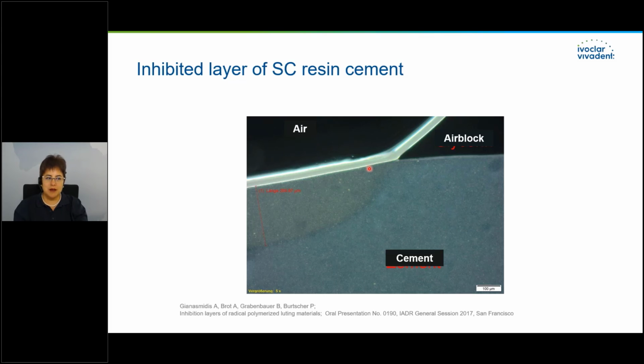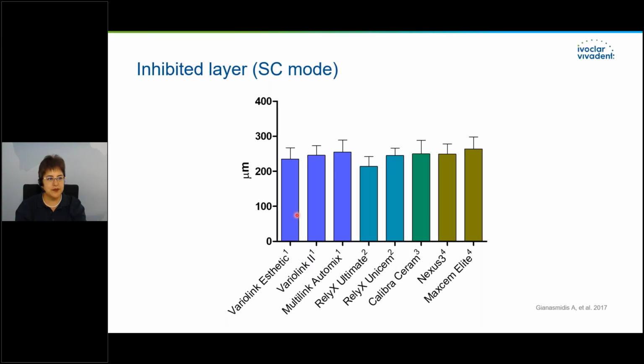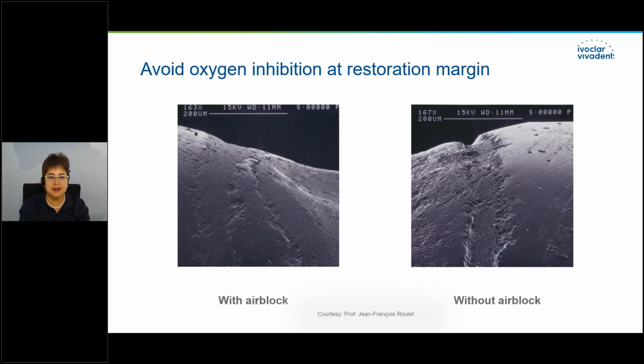If you are not applying it, then you will have a gap of around 265 microns of uncured resin on your margins. And this uncured material can lead to stainings and decolorations on your margins, and nobody wants this. Here also, using self-curing mode, you see the oxygen inhibition layer is around 200 microns or more depending on the material. If you light cure the material, this thickness will be much lower but still existing.